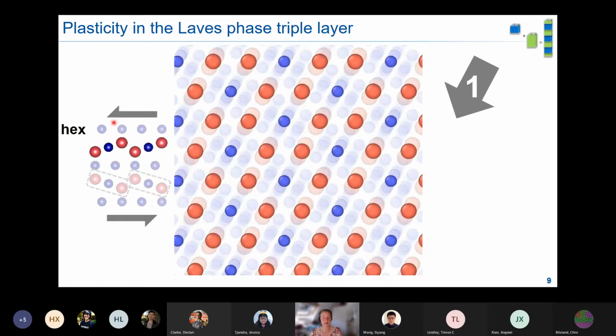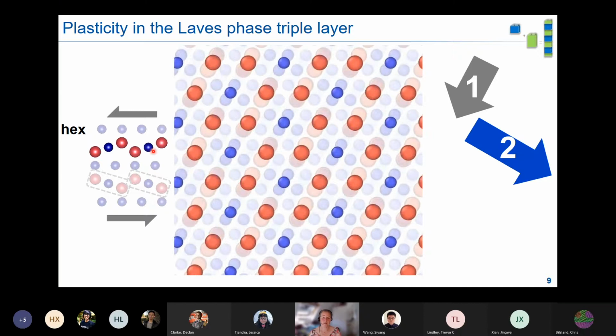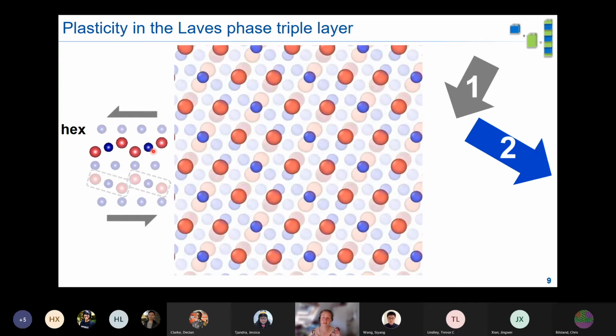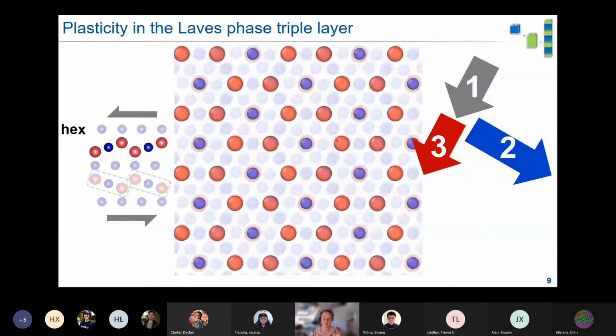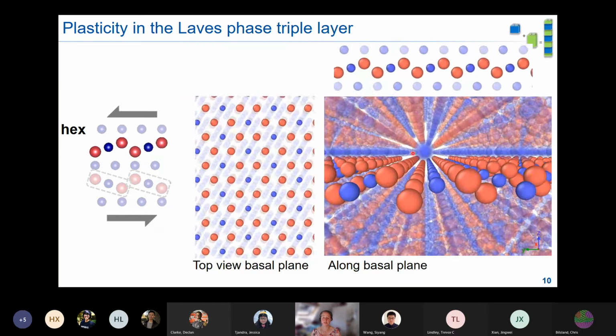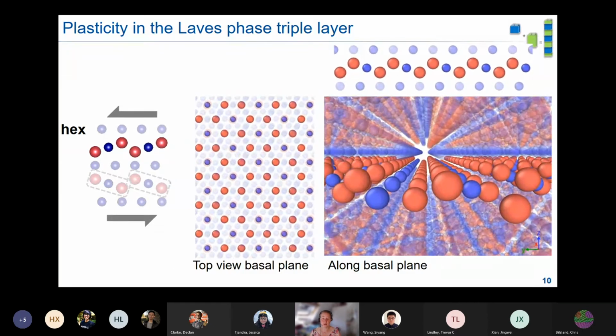There are atoms here in this triple layer who are nearly at the same height. And so what happens is that you then have a sideways movement of one plane in this lattice, and then the whole shear movement continues to arrive at a stacking fault. And so this whole process is called synchroshear, and that's what's happening in this simulation.